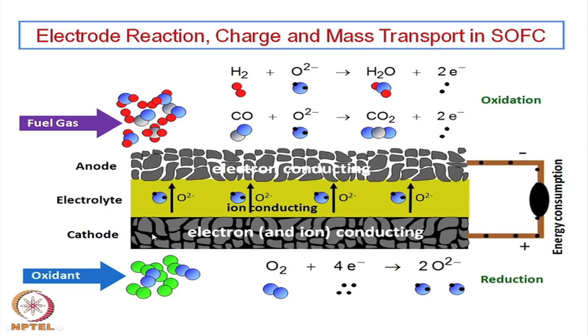So, the gaseous fuel or the gaseous oxidant has to come in contact with this interface, and the triple phase boundary, that means the cathode, electrolyte and the gaseous environment. So, these are the triple phase boundaries like this. These are the reaction sites where this kind of reaction is taking place. The oxygen, because this is the oxygen side, the cathode side: oxygen plus 4 electrons give rise to 2 O²⁻. So, at this interface this reaction is taking place.